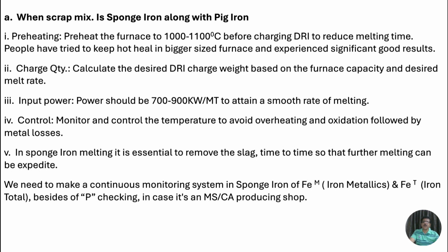Number five, in sponge iron melting, it is essential to remove the slag from time to time so that further melting can be expedited. We need to make a continuous monitoring system in sponge iron of iron metallic and FeT, iron total, besides phosphorus checking in case it is an MS or carbon alloy producing shop.